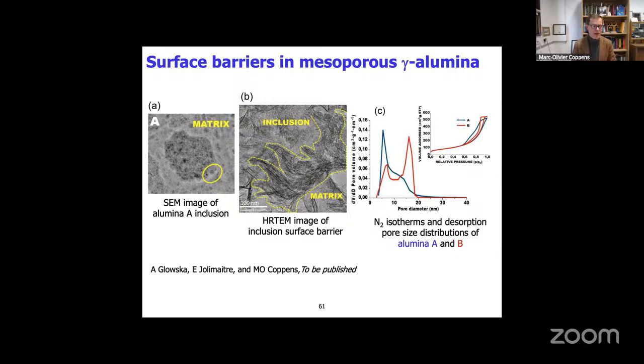Now we see these effects. So even these fudge factors that we use might work on interpreting one set of experiments, but if you extrapolate and use this for design or to interpret others, you will be off. That is the problem. You might see an effective diffusivity model that seems to work, but you're actually hiding the reality because you use simply that tortuosity to cover topology.